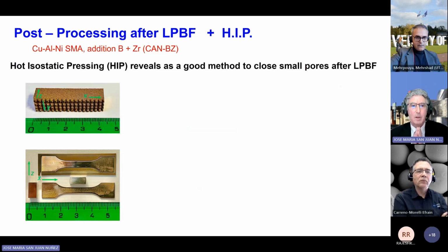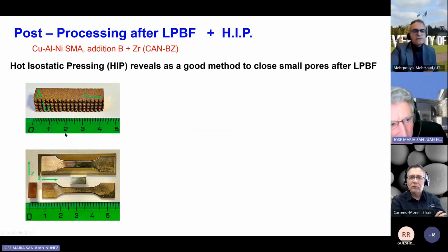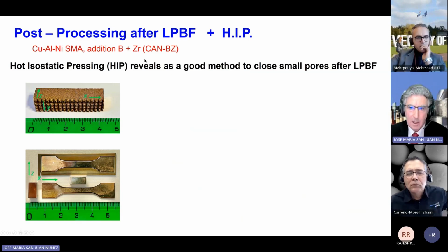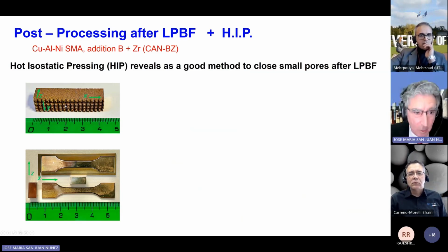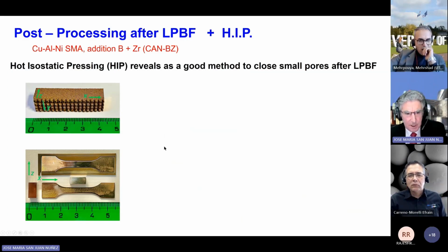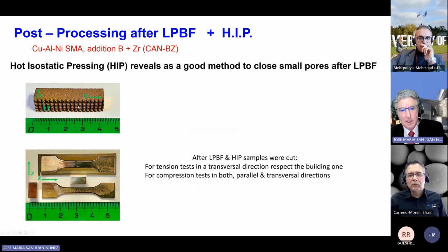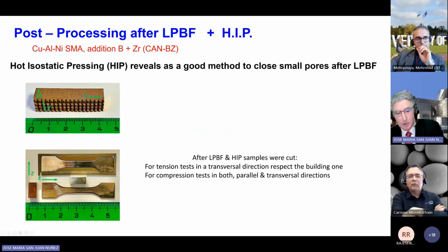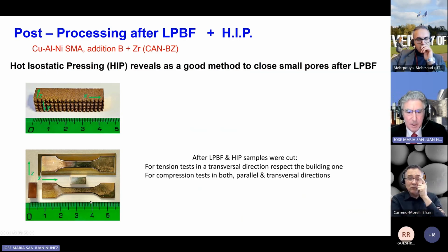So then let me move to another post-processing activity. Here you can see the sample grown by laser powder bed fusion. This is the growing direction. This is the lower part. Then from this material, after the laser powder bed fusion, we performed hot isostatic pressing, and then the samples were cut for tension tests in a transversal direction, because we cannot get a big sample in the other direction, because of the reduced volume setup we are using and the amount of material we have. And then for compression tests, we have cut samples in the transversal direction and also in the building direction, the direction of Z, in order to compare